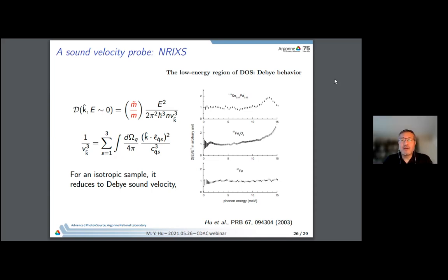No, because once it's going through liquid, the Lamb-Mössbauer factor becomes an issue, because then there's no recoilless absorption anymore. So you will get a broadened elastic peak, and then it's quasi-elastic. And then there's all kinds of diffusion phenomena coming in.